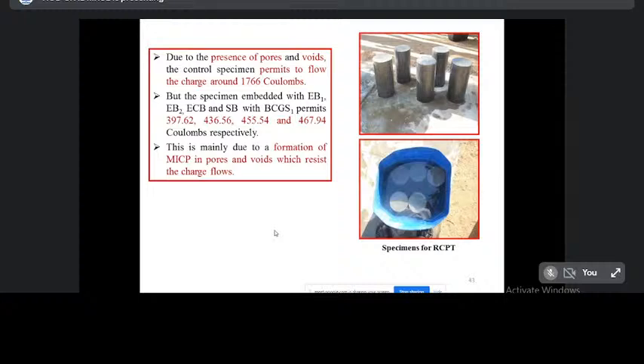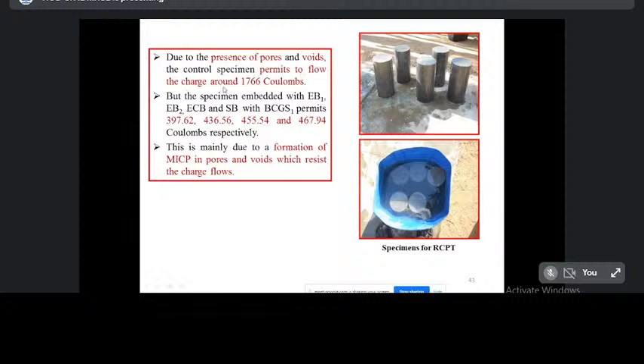From this test, we have concluded that due to the presence of pores and voids, the control specimen permits a flow charge of around 1766 coulombs. But the specimens embedded with EB1, EB2, ECB and SB with BCGS1 permit 397, 436, 455 and 467 coulombs respectively. As compared to control, this value is very low. This is mainly due to the formation of MICP in the pores and voids, which resists the flow charge.